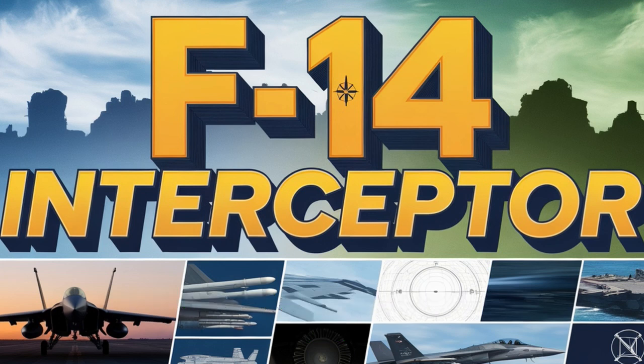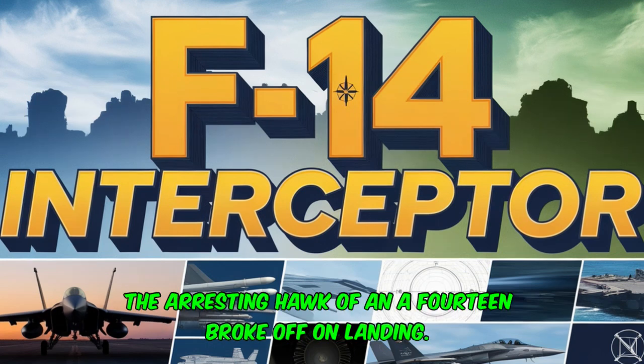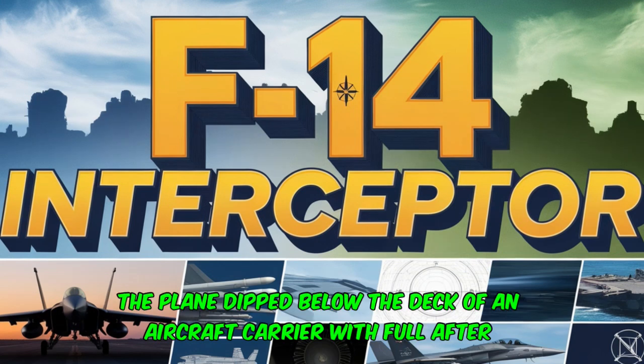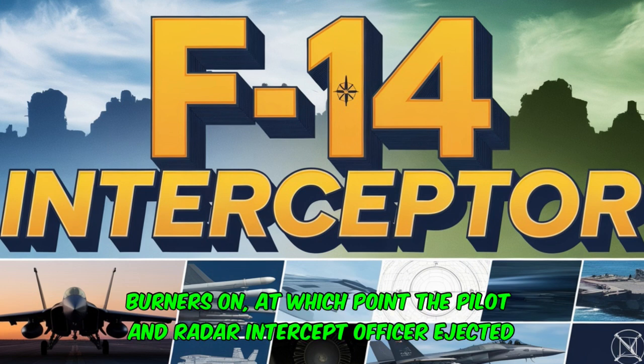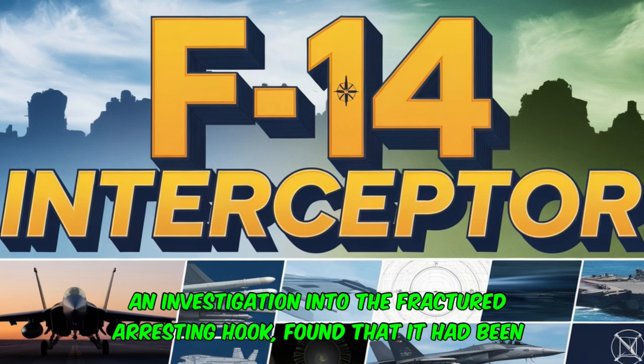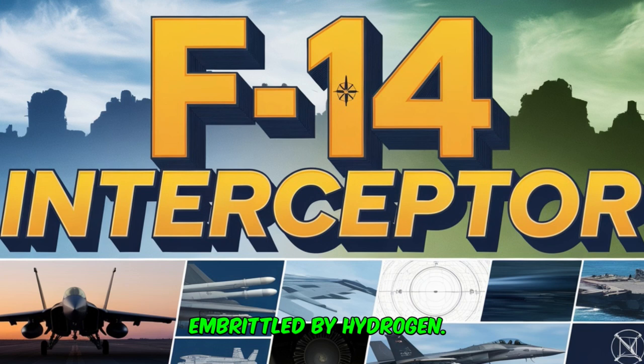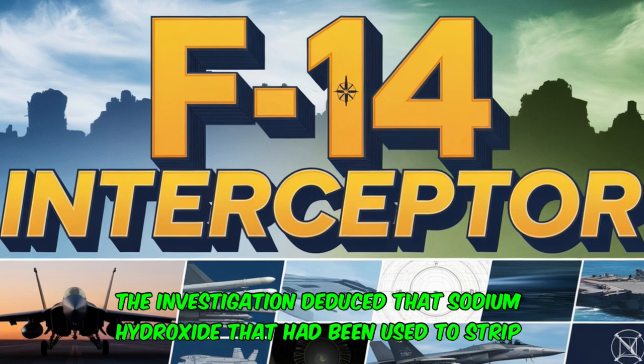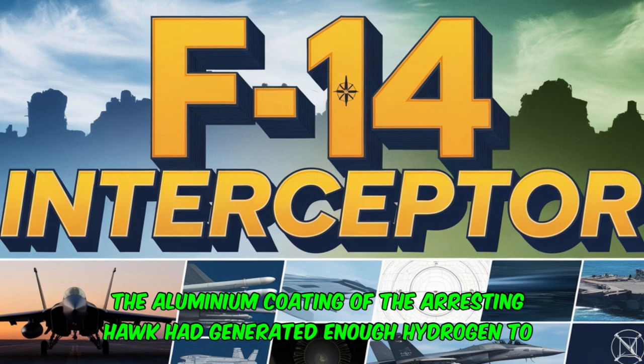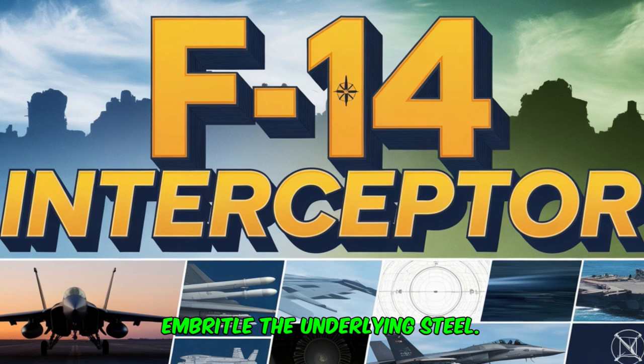In 2002, the arresting hook of an F-14 broke off on landing. The plane dipped below the deck of an aircraft carrier with full afterburners on, at which point the pilot and radar intercept officer ejected. An investigation into the fractured arresting hook found that it had been embrittled by hydrogen after a refurbishment. The investigation deduced that sodium hydroxide that had been used to strip the aluminium coating of the arresting hook had generated enough hydrogen to embrittle the underlying steel.